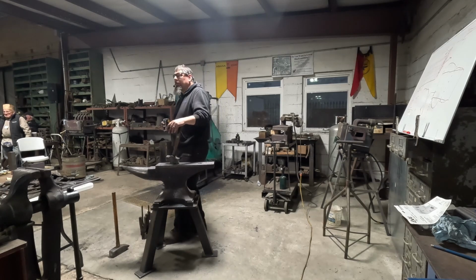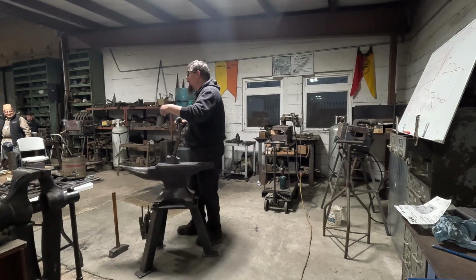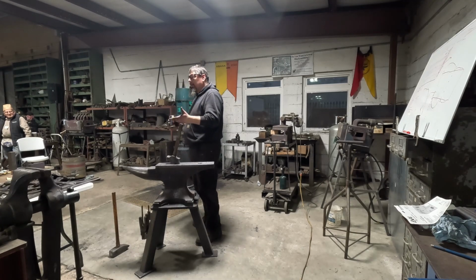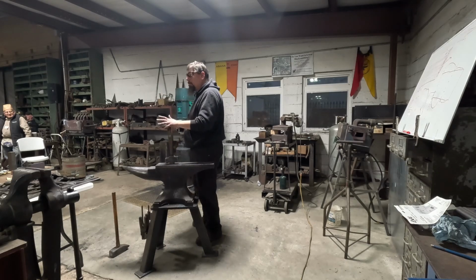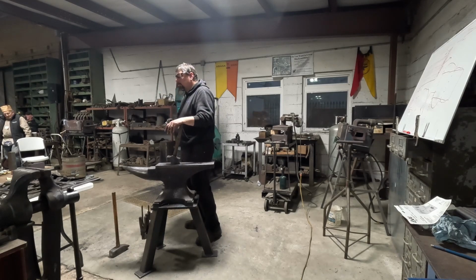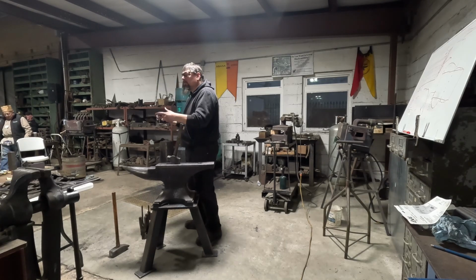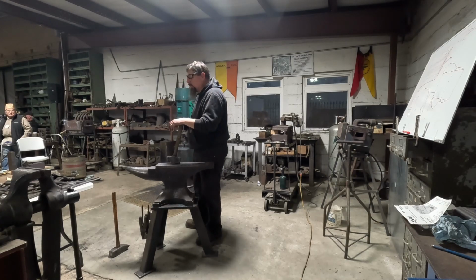But people still struggled with hot short steel. This is one of the reasons why someone was sharing, I think Peter was sharing, about Samuel Yellin inspecting raw materials that he ordered coming in, making sure that they would survive various forging tests like bending and welding and so forth, because if they were contaminated either with too much slag or with sulfur, they would behave like this, and that would of course be a problem. And so there have been for a long time physical tests, like the ones I did, that others have done, to establish whether or not materials are suitable for the kind of forge work that Samuel Yellin was doing.